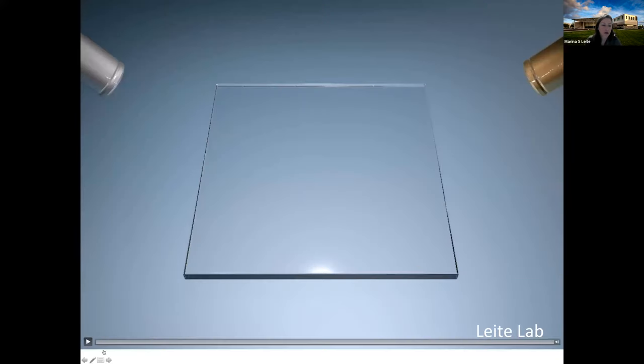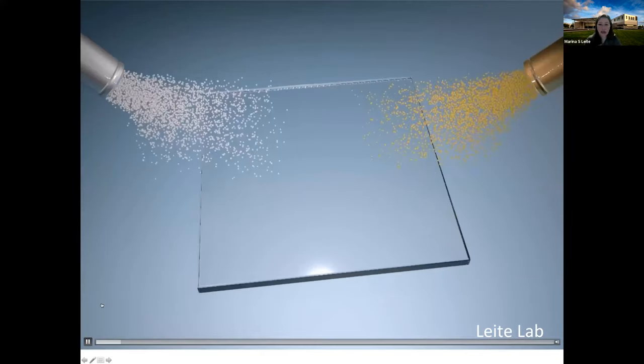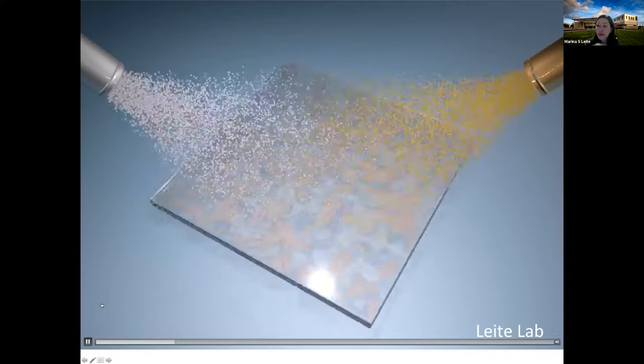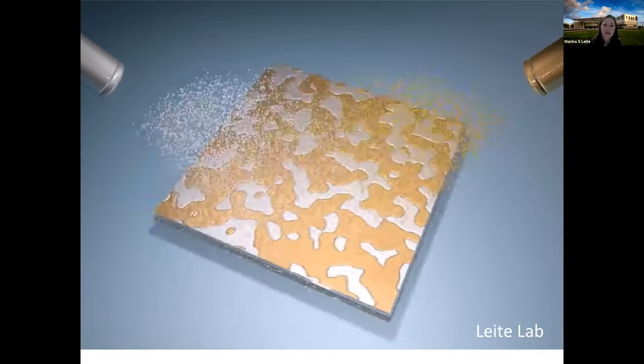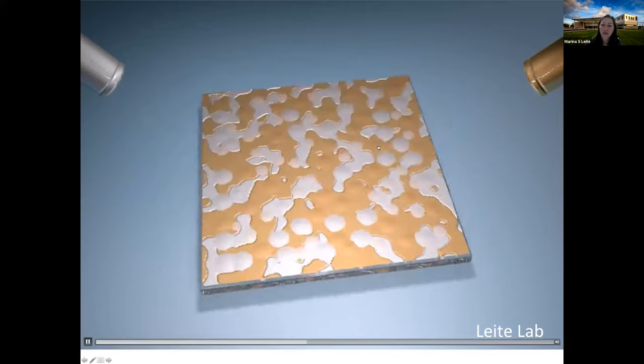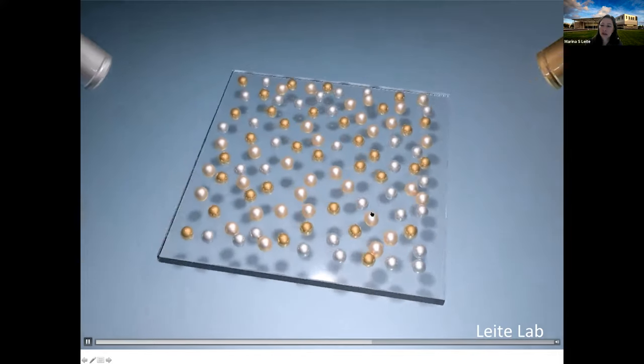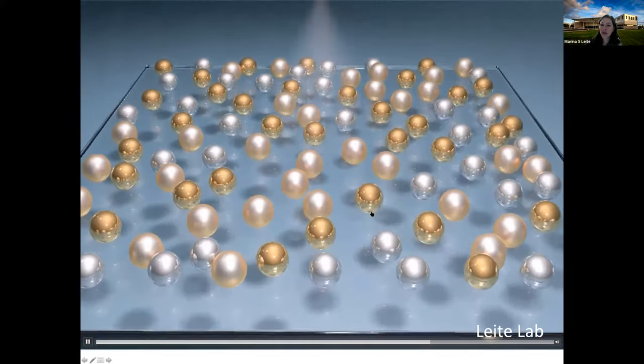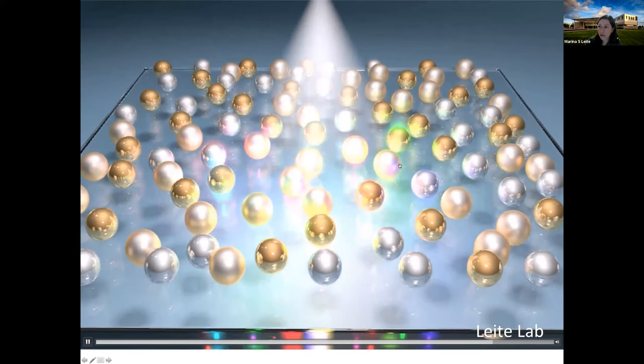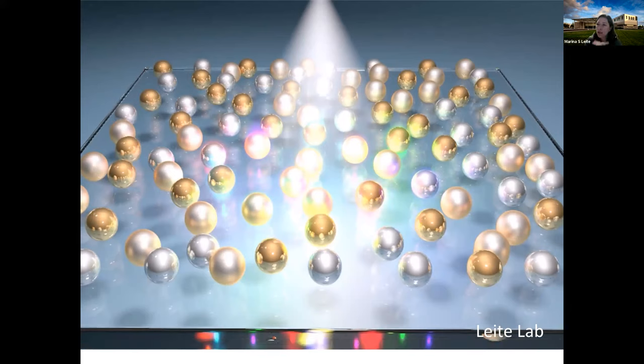Let's see if this video is going to play. The way we make these nanostructures in a scalable and very simple manner is that we do a co-deposition while we rotate the substrate, and then we do an annealing process in an oxygen-free environment, and voila, we have our nanoparticles. Then we can study the light-matter interactions. They form due to dewetting, essentially. I can give you more details on that if anyone is interested, just let me know.